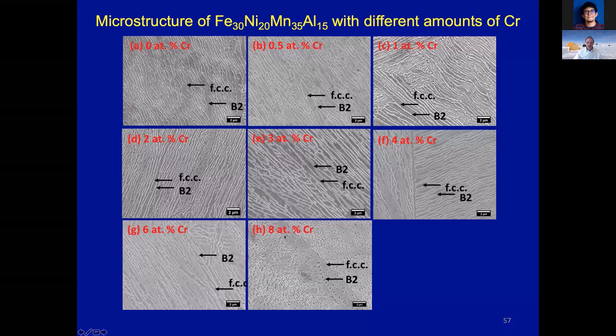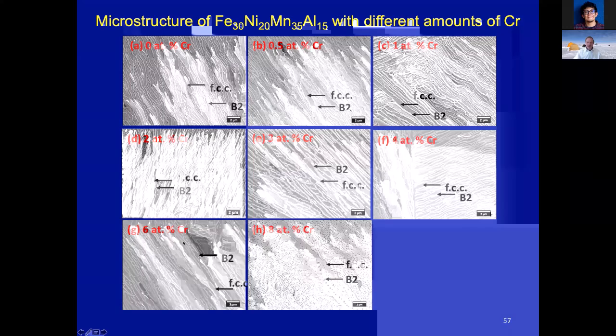One of the things we decided to do to try and fix this environmental effect was add chromium to the material. This is the material we started out with, with no chromium, and these are different amounts of chromium, going from 0.5 through 1, 2, 3, 4, 6 atomic percent, and 8 atomic percent. By the time we get to 8 atomic percent, the microstructure has actually changed. Up to 6 atomic percent chromium, it's essentially the same lamellar spacing and structure as the material without chromium.